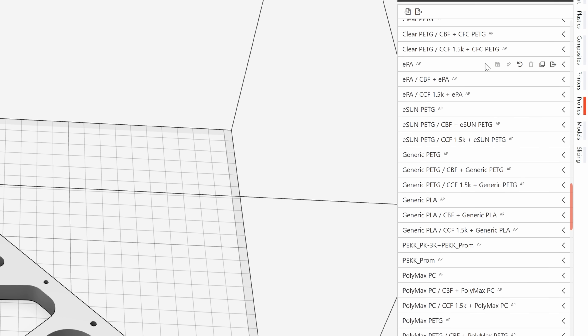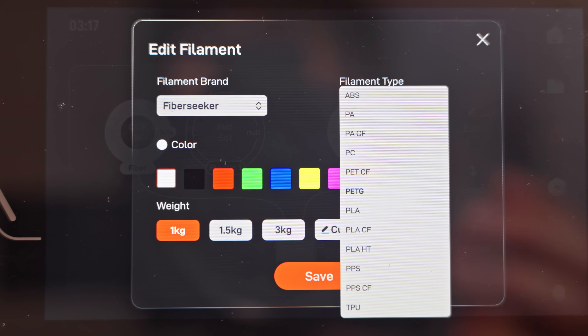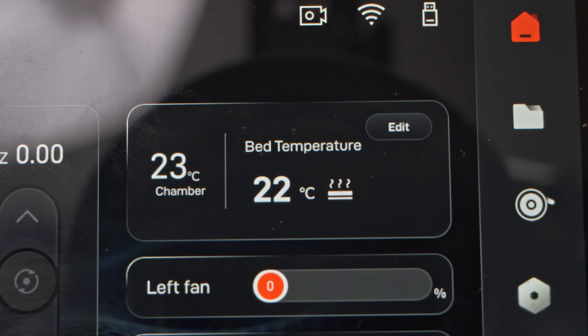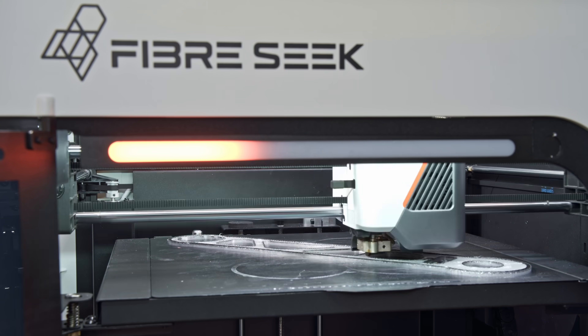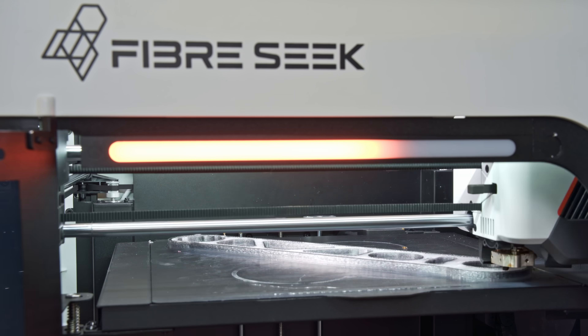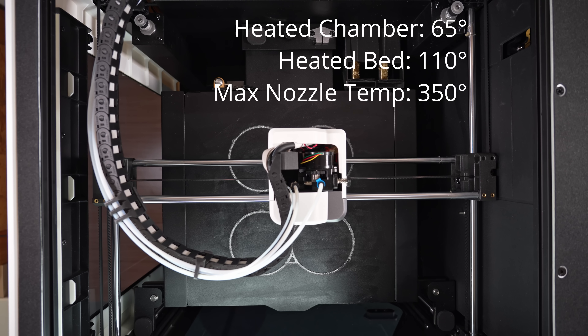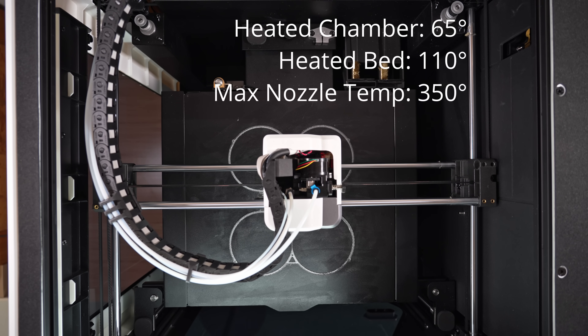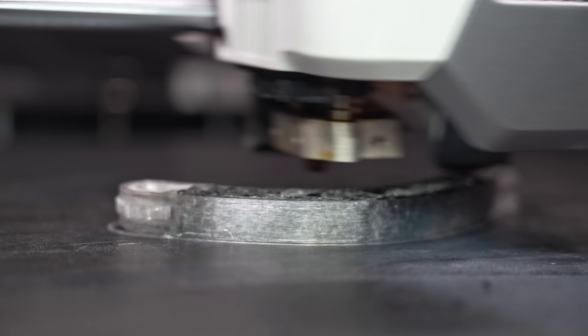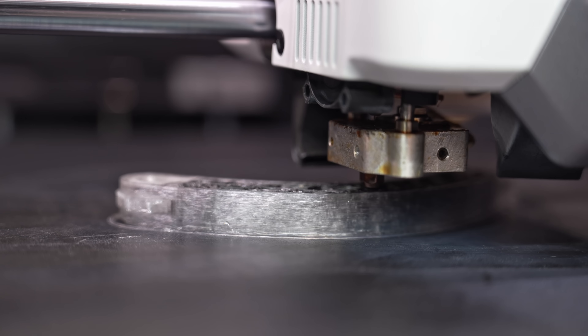This machine will work with any type of filament, and it includes a few features that make it a serious contender for advanced engineering filaments, including a heated chamber capable of going up to 65 degrees Celsius. That will definitely help with warping on ABS and nylon, and this printer excels at printing large parts. The nozzles are hardened steel and can reach 350 degrees, the heated bed goes up to 110, and the standard FDM nozzle prints at up to 500 millimeters per second.